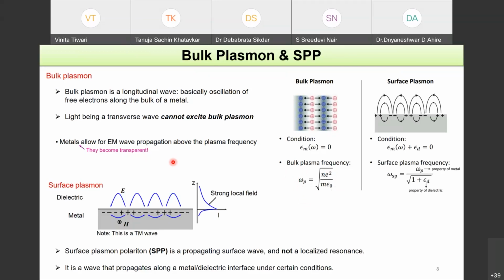How about surface plasmons? So this is bulk plasmon and this one is surface plasmon. It is very clear that the surface plasmon exists at the boundary between metal and dielectric. If you think of a metal dielectric interface and evanescent waves, you'll see that the waves are penetrating more into the dielectric side, but they are actually propagating along the interface. This is called surface plasmon polariton. It is basically a propagating surface wave, and it's not a localized resonance.